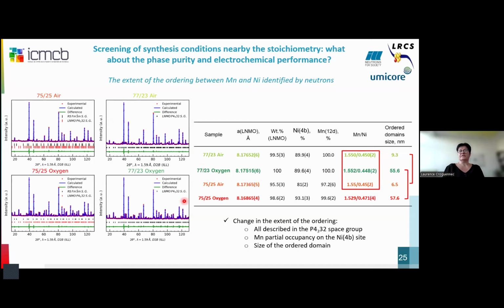Now, if we move to these stoichiometric materials here in orange and red, you can see that for the red one, stoichiometric under oxygen, we are almost at the perfect distribution between the two sites. And we also have a big size for the ordered domain. And again, under air, much smaller domain size and similar distribution and mixing versus the manganese-rich materials.